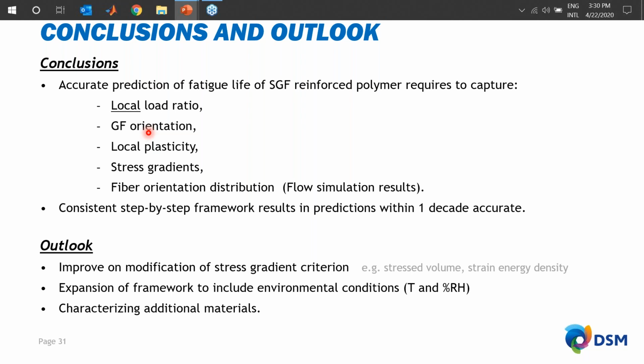Okay. Another question here: do your models only apply to in-plane fatigue, or could they address out-of-plane stress details as well? Yeah, at this moment we only look at in-plane, that's correct. But actually for the part, you'll also look at multi-axiality. So you look at the max principal stress, that is the main driver for, let's say, the gradient correction. But besides that, the failure indicators are computed using the multi-axial stresses. So actually it can also look at out-of-plane stresses and take those into account. I think that is the strength of this calibration of the anisotropic material model.